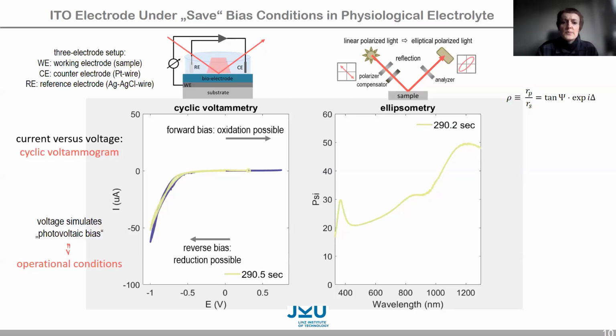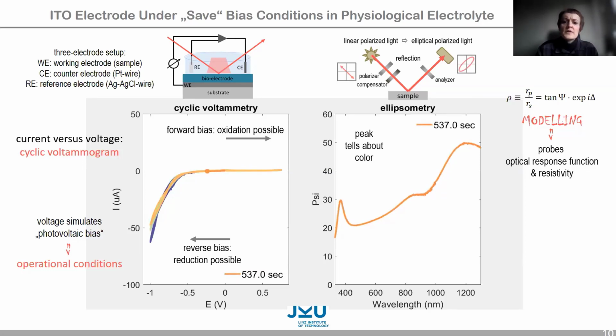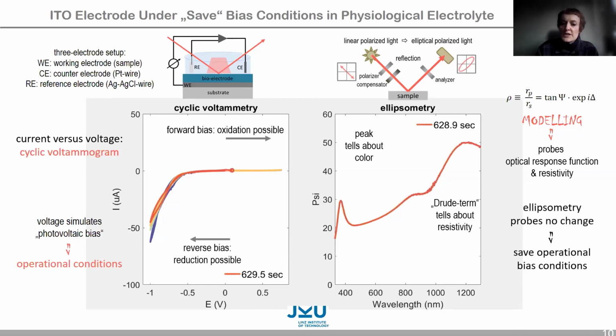Simultaneously, a polarized light beam probes the optical and electrical properties of the ITO sample under voltage bias by changing its own polarization properties. The value psi, which is plotted against the wavelength of the probe beam, is a rather abstract value, and modeling is required to extract the sample properties. Simply speaking, the peak at short wavelength tells you something about the color of the sample, and the peak at longer wavelength, called Drude term, tells you about the resistivity of the sample. Here you can see no change for the ellipsometric recording, and this means that the sample, here the ITO electrode, remains unchanged and stable under the applied bias conditions.